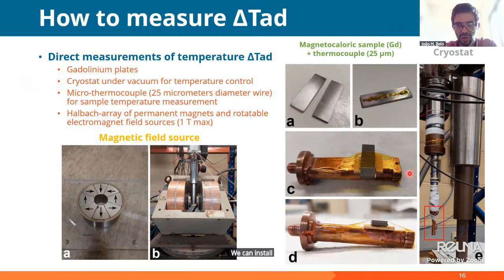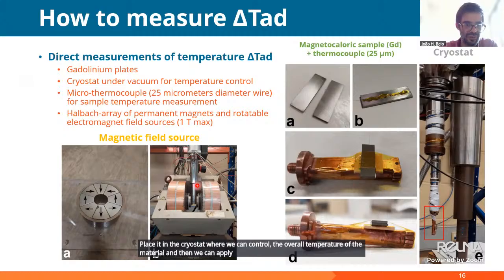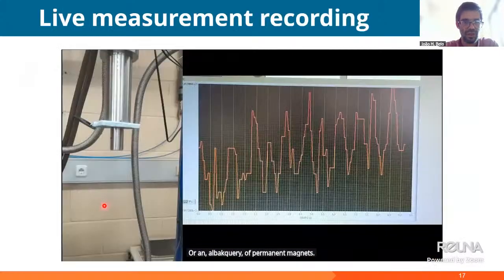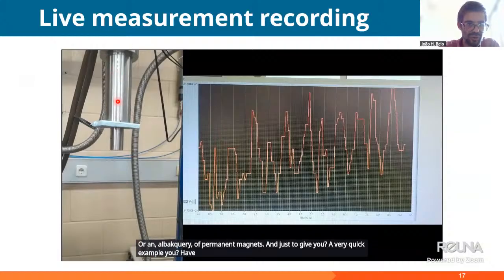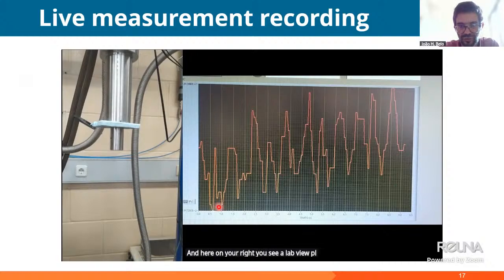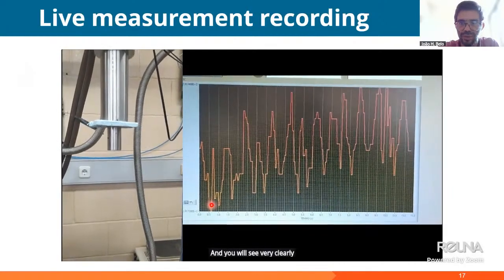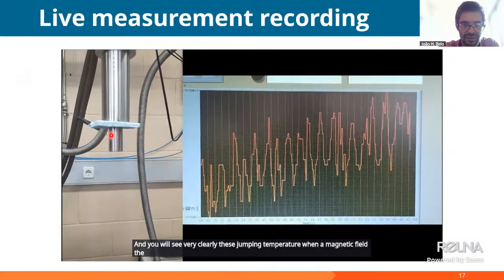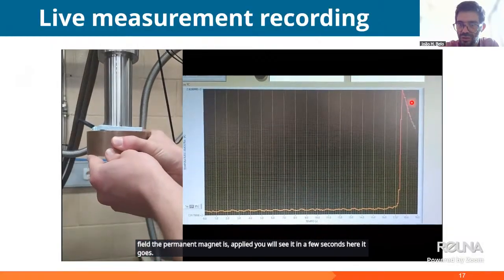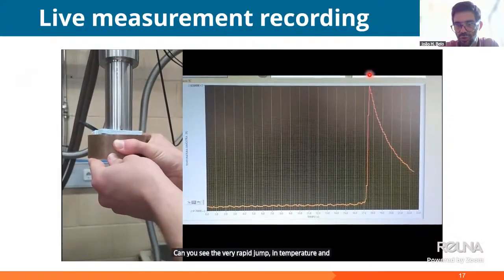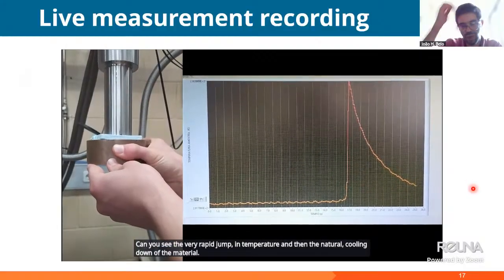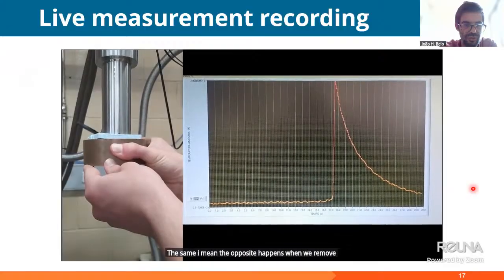We can install it in a copper cold finger, place it in the cryostat where we can control the overall temperature of the material, and then we can apply magnetic fields using either an electromagnet or a Halbach array of permanent magnets. Just to give you a very quick example, you have here the same cryostat that I showed you in the previous slide, but now closed. And here on your right, you see a LabView plot of the temperature versus time. You will see very clearly this jump in temperature when a magnetic field, the permanent magnet, is applied. You will see it in a few seconds. Here it goes. And you see the very rapid jump in temperature and then the natural cooling down of the material. The opposite happens when we remove the field, as you will see now.